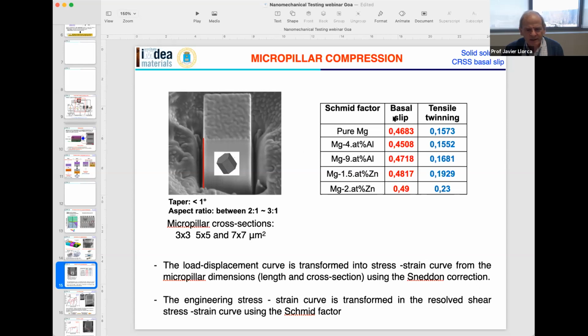And as you can see here, the Schmid factor for basal slip in all these cases is very high, very close to 0.5, while the other potential deformation mechanism that you can activate, that is twinning, has a much smaller Schmid factor. So because the critical resolved shear stress for basal slip is the smallest one, and because of the difference in Schmid factor, we are almost sure that when we do the deformation, we are only going to activate basal slip. And as you can see here, we are going to measure the critical resolved shear stress in pure magnesium, magnesium 4 atomic percent aluminum, magnesium 9 atomic percent aluminum, and then magnesium 1.5 and 2 atomic percent zinc. So that means that we have a lot of different compositions.